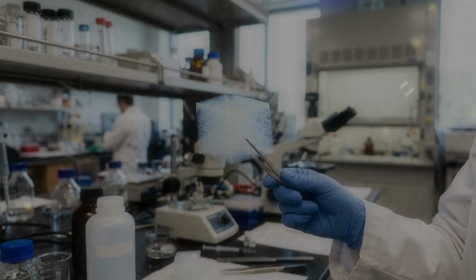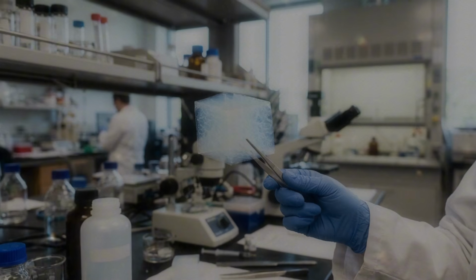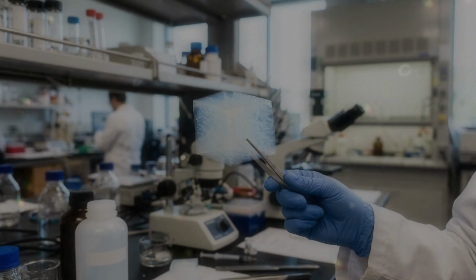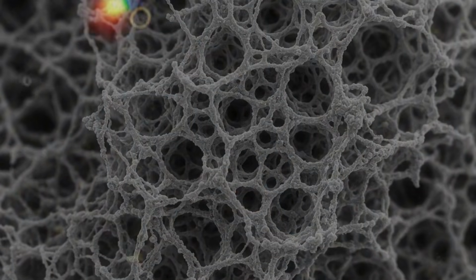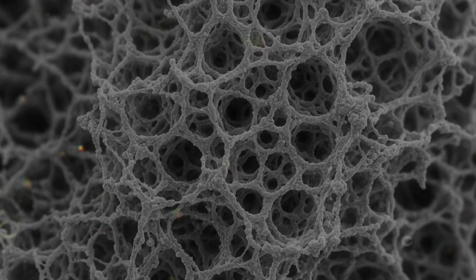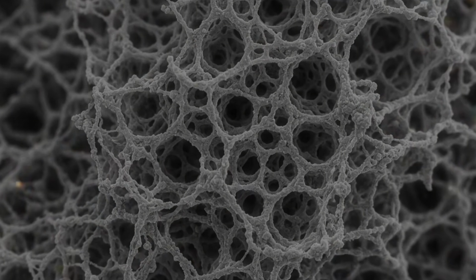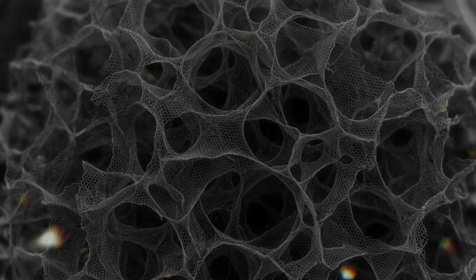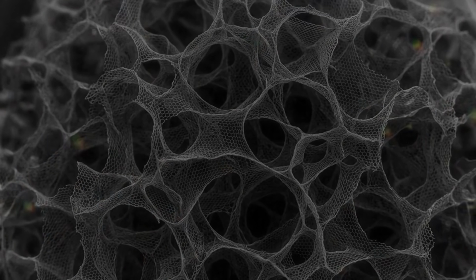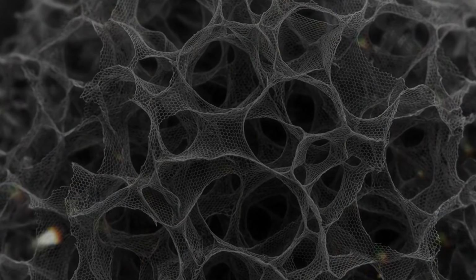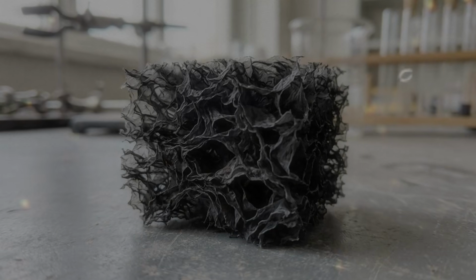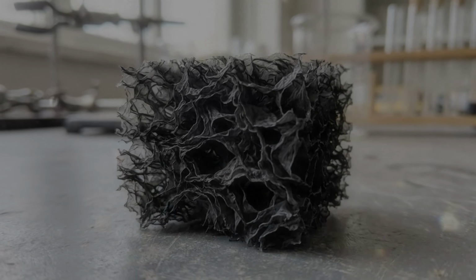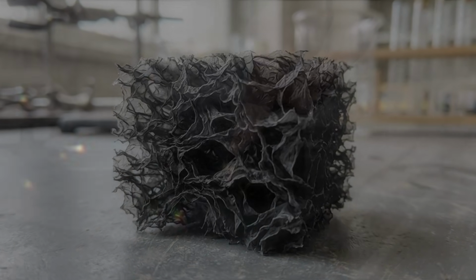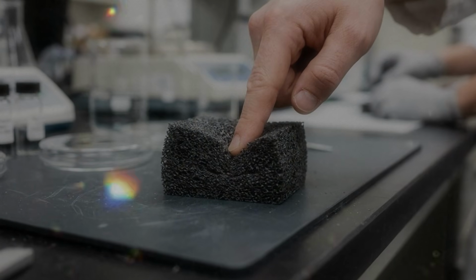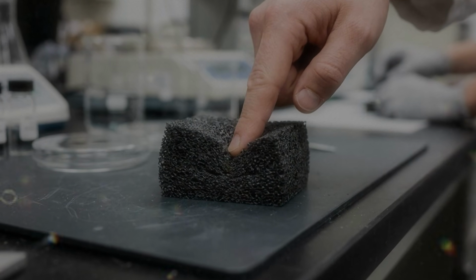The shape of each pore also influences mechanical behaviour. Round openings distribute force differently from long narrow ones. Irregular cells may collapse in stages. Aligned channels can make the material stronger in one direction and weaker in another. If the pores are all arranged vertically, the sample may support pressure from above while bending more easily from the side. This directional behaviour is called anisotropy. It appears whenever a material has an internal arrangement that favours one direction. Wood is a familiar example. It splits more easily along the grain than across it.